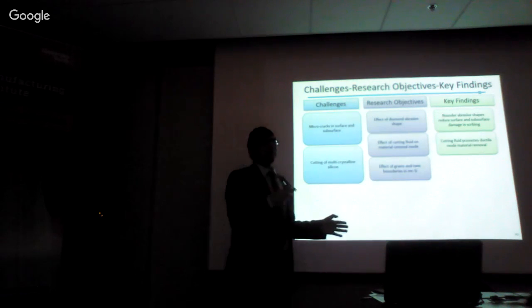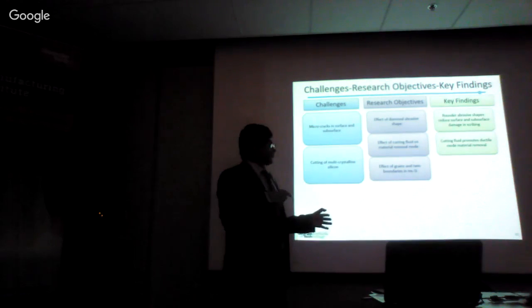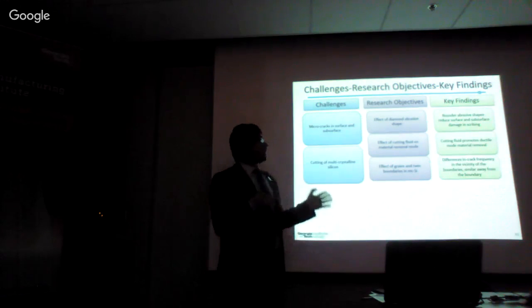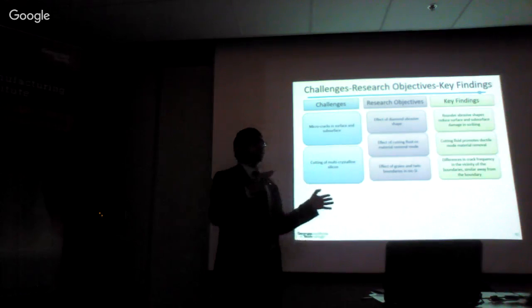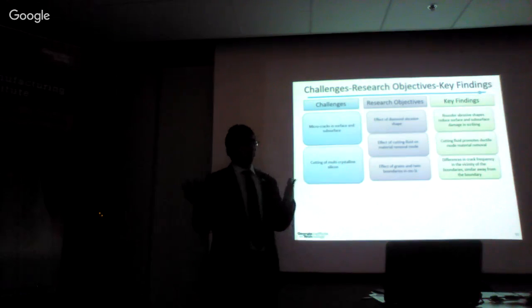The next challenge was cutting multi-crystalline silicon because of the grain and twin boundaries, apart from other inclusions and carbides and nitrides, which was one of our research objectives, to find the effect of grain and twin boundaries. And we found that there is a difference in crack frequency in the vicinity of the boundaries, but the crack frequency becomes similar away from the boundary in adjacent grains.